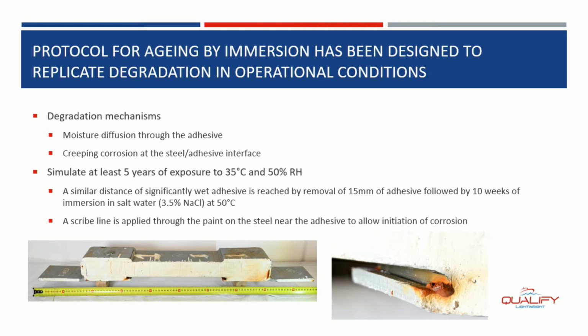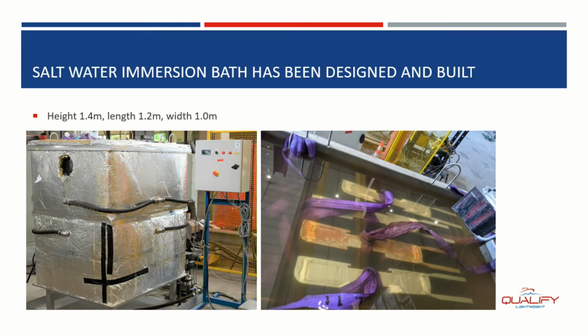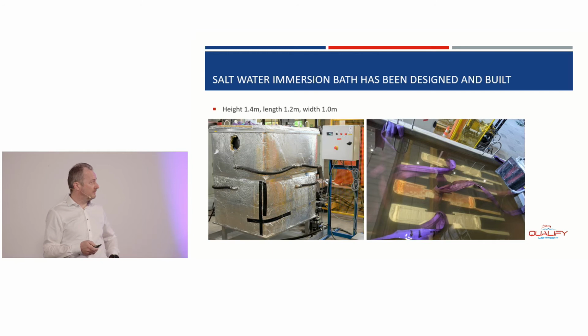To allow this to be done on these very large specimens, we had to design a saltwater immersion bath. You see a few of the dimensions here. It holds a little more than 1.5 cubic meters. The setup is fully controlled to have a stable temperature at 50 plus or minus 0.5 degrees Celsius. Salinity is controlled. You see some tubes for continuous recirculation of water so that we have very homogeneous saltwater content, but also very homogeneous temperature at all locations of the specimens. At the right, you see that we are able to put, for example, 4 Arcan specimens, very large specimens, together with the tensile specimens in that bath, to reduce the total testing time, because we are dealing with 10 weeks of immersion before we can start the testing.